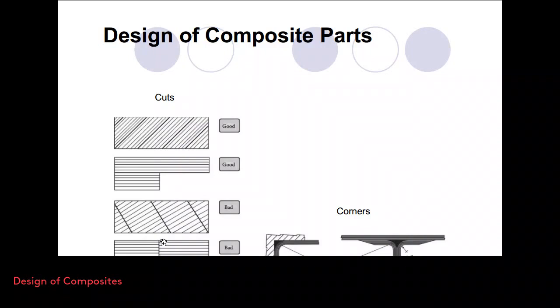In fact, it is the same in this placement of the fabric. Certainly the ends will not carry too much load, and as a result you decrease the load bearing capability. You possibly see the failure here and also here, because we know that the matrix is capable of carrying less load. Another problem that we face is the corners. Now we have the fabric and we cover the fabric with the resin. In fact, it is not possible to have a sharp corner. This basically means that we are going to have spaces at the sharp corners, as you see in the figures.